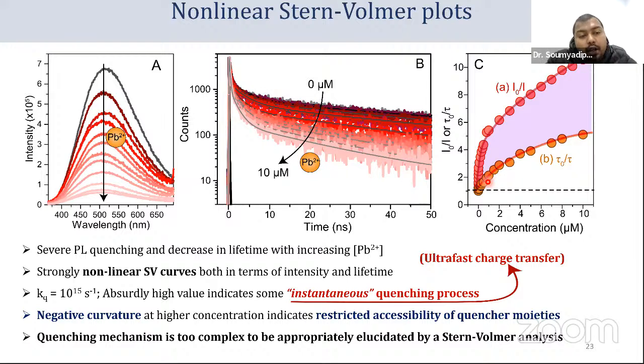So with addition of Pb2+, you can see there's a severe quenching of photoluminescence of the cadmium sulfide quantum dots, more than 85%. And when we plotted the Stern-Volmer plot, it's totally nonlinear. We then plotted the modified Stern-Volmer plot, and it was still nonlinear. So there is something going on which cannot be explained in the conventional way.